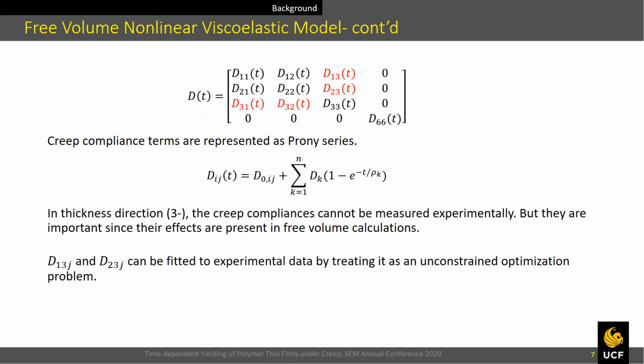Here D is the creep compliance tensor, and the individual elements of the tensor are represented by Prony series. The out-of-plane creep compliances D13 and D23 are important since their value will change the free volume and affect the material response. In thickness direction, since the material is very thin, the creep compliances cannot be measured experimentally. D13 and D23 Prony series terms can be fitted to experimental data by treating it as an unconstrained optimization problem.